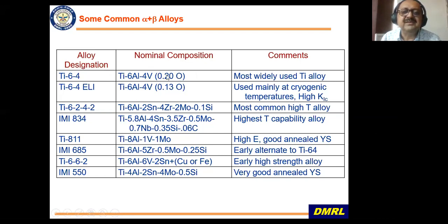One is normal Ti6Al4V, which has a higher amount of oxygen, and strengths are higher, and another which is used for formability applications is known as ELI grade, which stands for extra low interstitials, where the oxygen and other interstitials are limited. And then we also have near alpha alloys which are used for high temperature applications. Here 6242 is the high temperature titanium alloy which the Americans use for their aero engine application. IMI 834 is one of the conventional titanium alloys with the highest temperature capability. But mind you, the maximum temperature at which you use conventional titanium alloys is only up to 600 degrees centigrade. Okay, not higher than that.